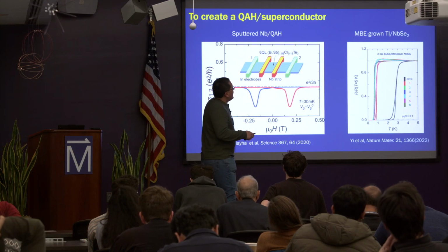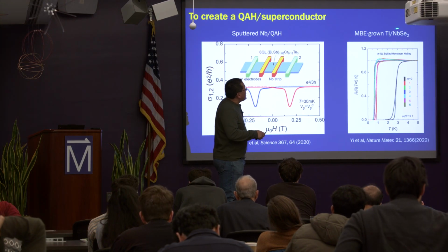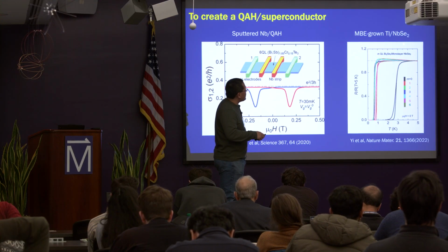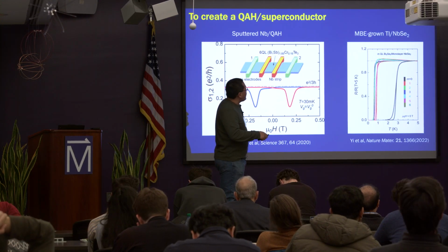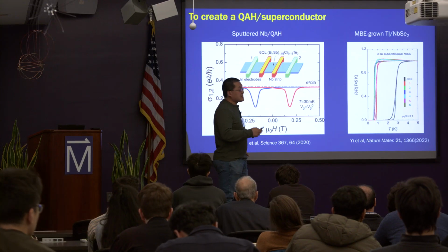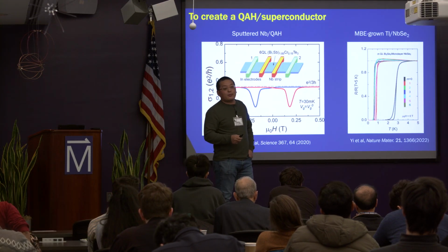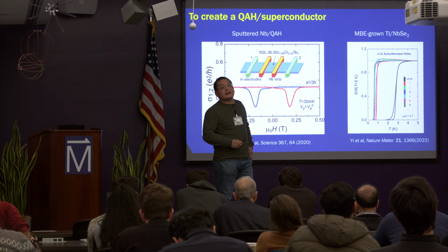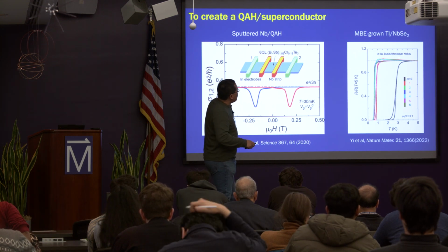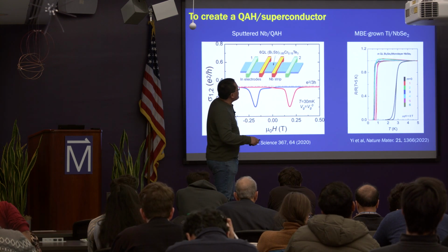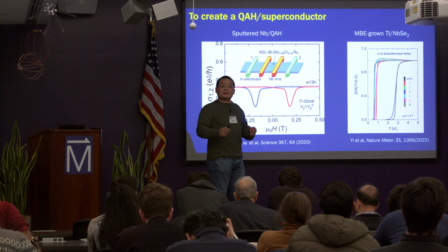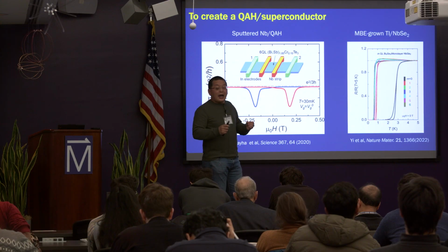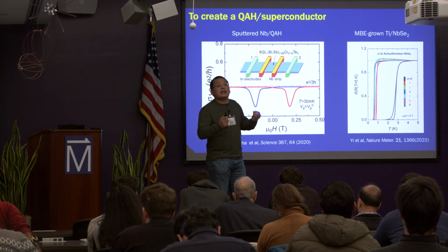So the first superconductor we tried is niobium selenide, which is hexagonal. We grew monolayer niobium selenide. The Tc is around 3 Kelvin, which is reasonable and comparable to the exfoliated monolayer. But we found that if you grow bismuth selenide on top of niobium selenide, the superconductivity will be greatly reduced, and sometimes it's completely killed.